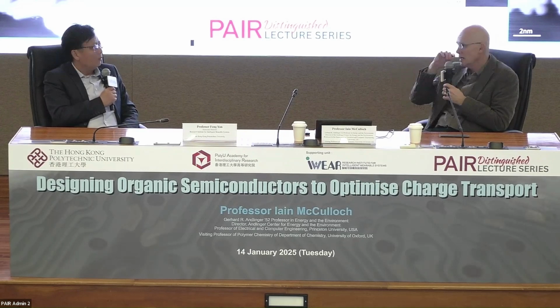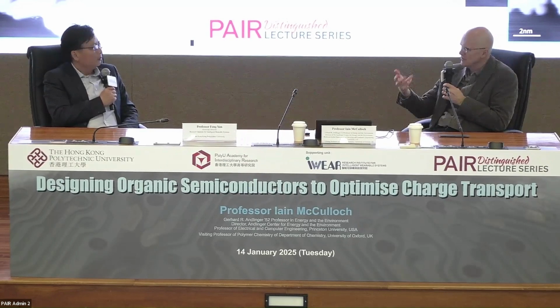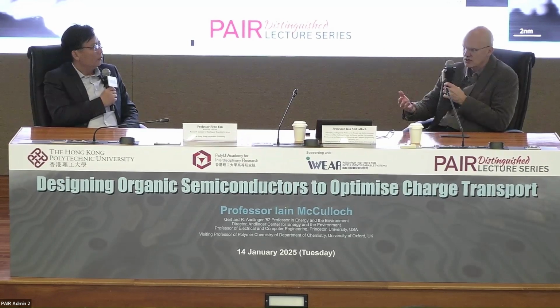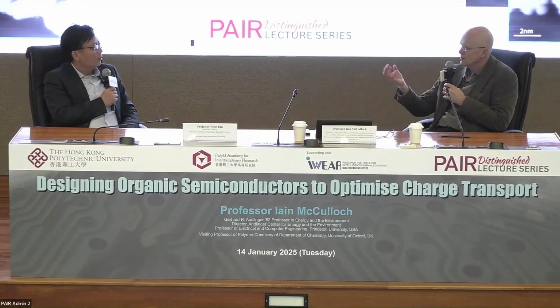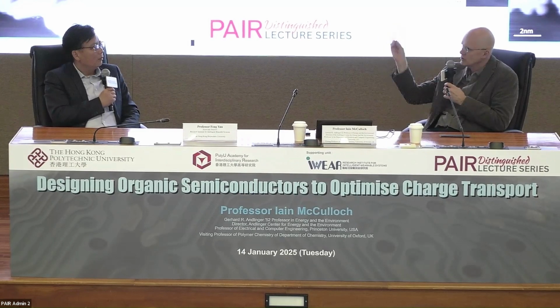Although if you look into BBL, it has a lot of porosity in the way that it's fabricated, because it's not a very soluble polymer. The poor solubility actually works to its advantage because you generate a lot of micropores in there. That allows ionic channels, even though you've got no side chains. And I think that's the perfect model as a polymer without the propensity to swell, but the ability to uptake ions. And it's not easy, because if it doesn't swell, it's hard to dissolve it, to fabricate it.